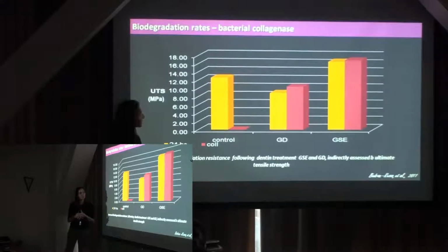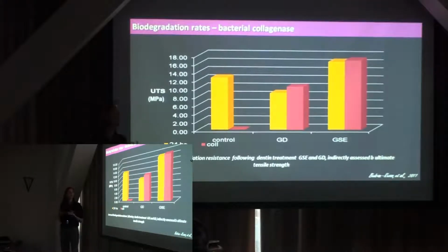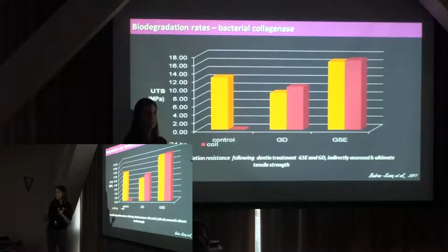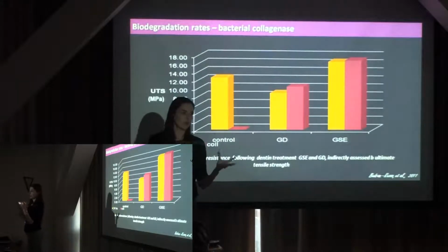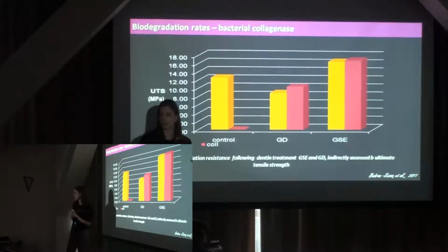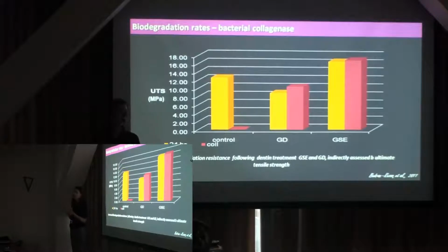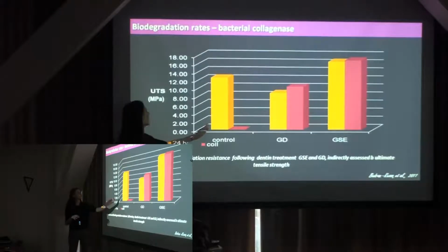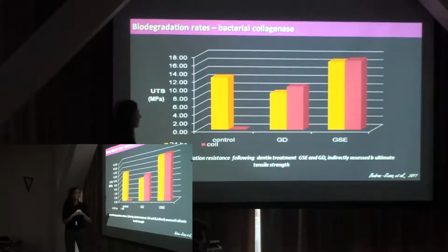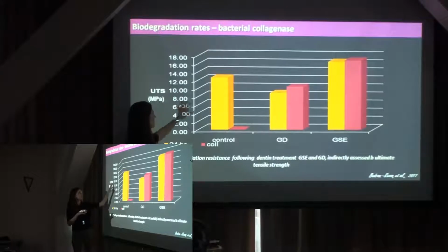Then a quick and dirty way to do some of these evaluations in the lab is we purchase collagenase. We use a buffer where we activate the collagenase over a 24-hour period. And what we get is these extracellular matrices, and we test them first. We look at their initial values. Well, actually, this was ultimate tensile strength.